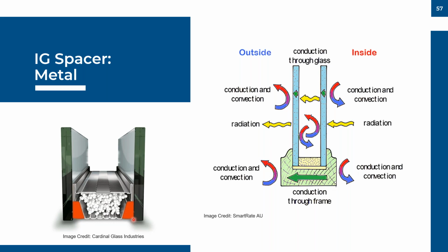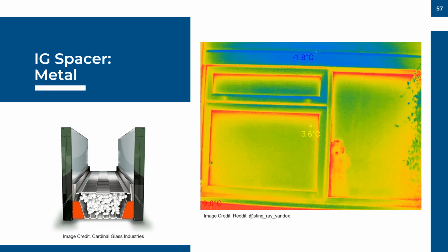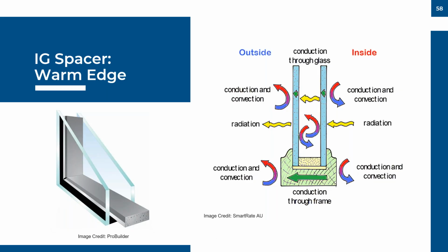Now, what happens on these is that if you have a very high performing insulated glass and argon gas and low E coatings, you can see that the center of glass performs very well, but the edge of glass is still relatively warm. This is viewed from the outside, where a lot of energy is still coming through the edge, and those edges can account for about 10% of the overall area of the window. So that's one way to improve, is to take a look at the spacers.